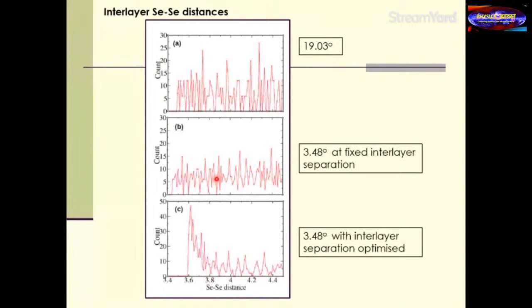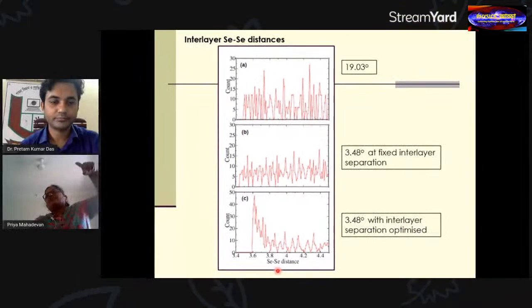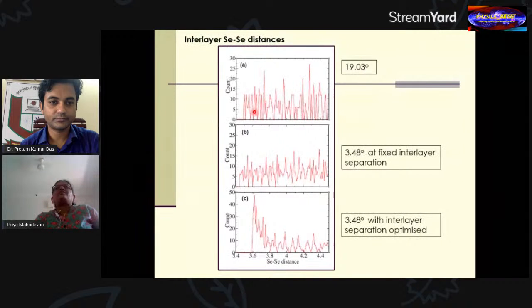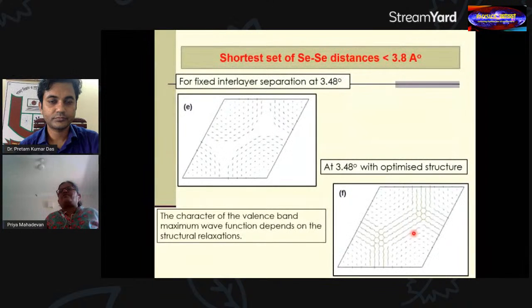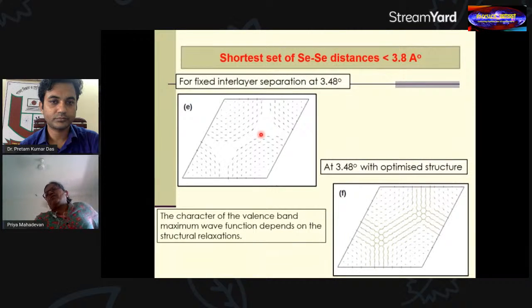Okay, so if you plot it as a function of the distances of the anions in the two outermost layers, what you can see is that this is similar, slightly different. We see the split-off band. So what we did was we looked at a profile of where the distances fall, and you can see that in both these cases, even at the small angle, we had fixed the separation between the layers. These are selenium distances, or you can extrapolate that to the hopping interaction strength, and they seem to be concentrated in some regions in these two cases.